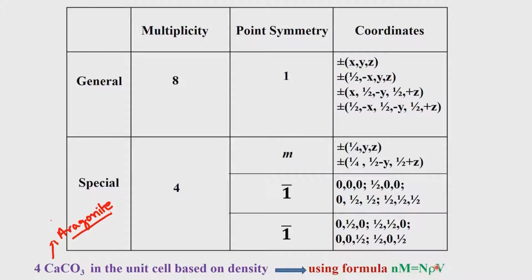but this method is quite expensive to do, because we have to, number 1, grow the crystals, number 2, determine the volume by X-ray diffraction experiments, determine the density by flotation, and then calculate the M value. So, it is going to be a tedious one. Instead, one can use the routine methodology that is available for molecular weight determination.